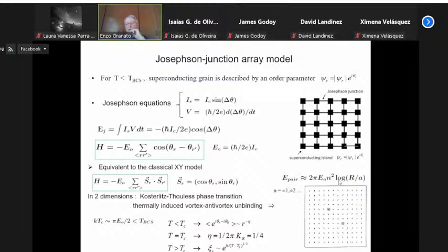The interaction energy between them is logarithmic, so it increases with the distance for opposite vortices. Those vortices, generated thermally at low temperature, are bound in pairs, but above the transition they are free to move around and give an exponential correlation. So the transition, therefore, is driven by the unbinding of such vortices.